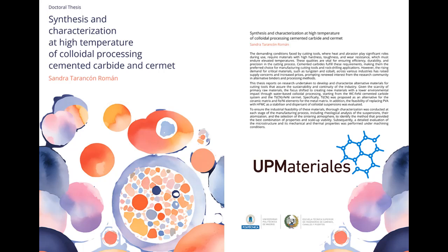Fascinating. Did they analyze the size of those atomized powders? I imagine that would be important for how well they eventually bond together. Absolutely. They did detailed particle size analysis to understand the range of sizes they had. And there's a general guideline in powder metallurgy that for optimal sintering, the ratio between the smallest and largest particle sizes shouldn't exceed 1 to 10. Okay, so there needs to be some consistency in size. Right. And Figure 3.7 and Table 3.2 present their findings. For the tungsten carbide iron nickel material, they found a pretty uniform distribution of particle sizes, with an average size around 16 micrometers. But for the titanium carbonitride iron nickel powder, there were actually two distinct groups of particle sizes, one around 7 micrometers and another around 19 micrometers, so a bit more variability there.